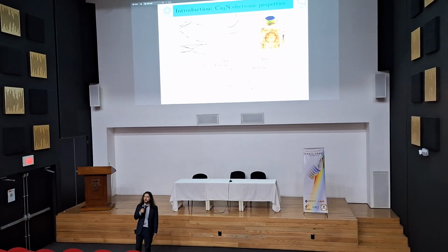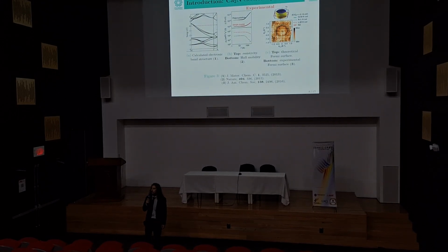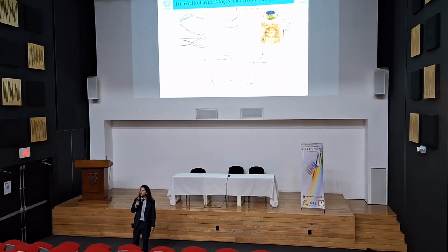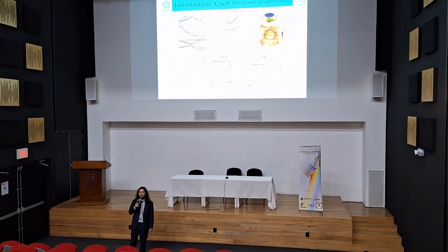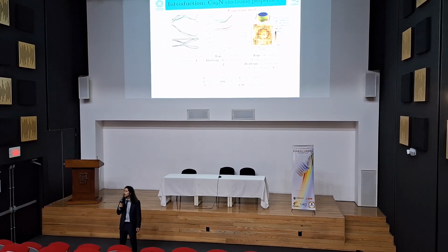In 2013, a first-principles calculation was conducted to obtain the band structure, which showed 3 bands crossing the Fermi level, and this means that the material has conduction in the plane parallel to the layers.